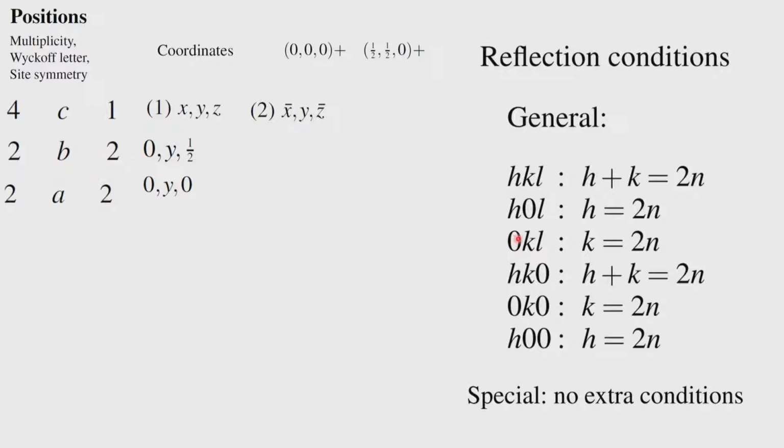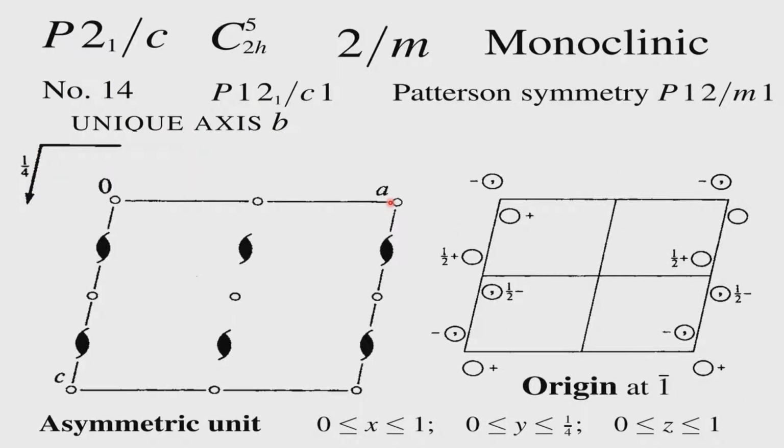All right. Having noticed this, we will go to the next system, which is the most common system we come across when dealing with organic structures. P21 upon C, the full symbol is P 1 21 by c 1, and it has symmetry positions like this. We have the center of symmetry, the twofold axis, and the C glide at 1/4 above the plane.